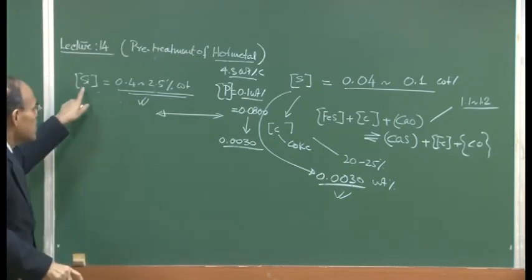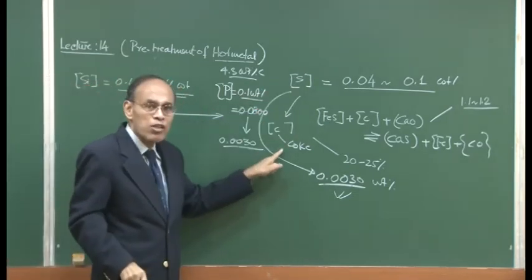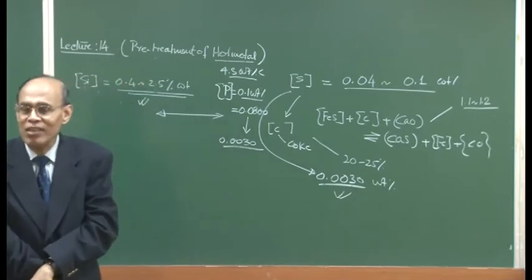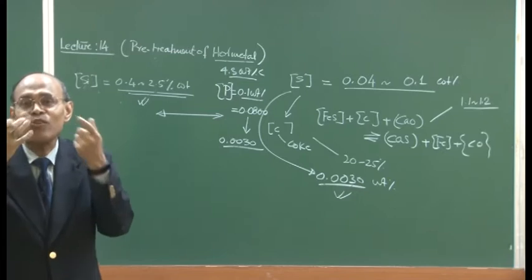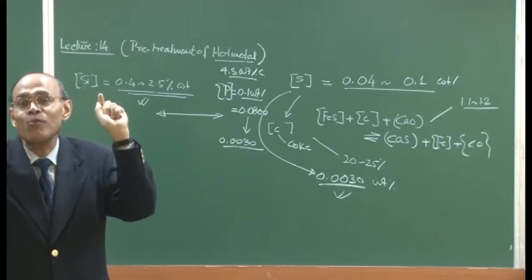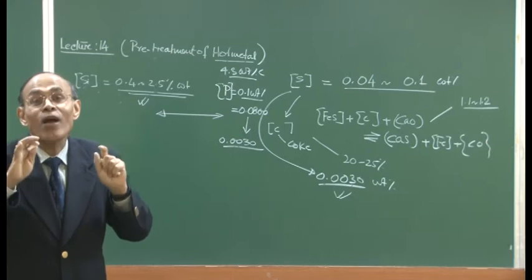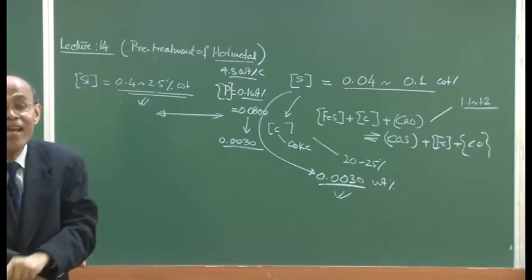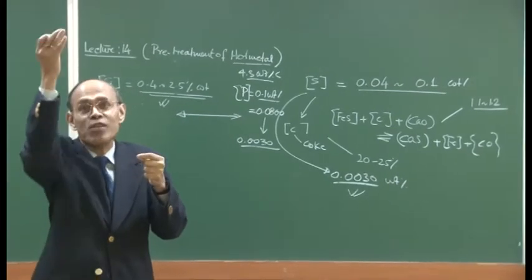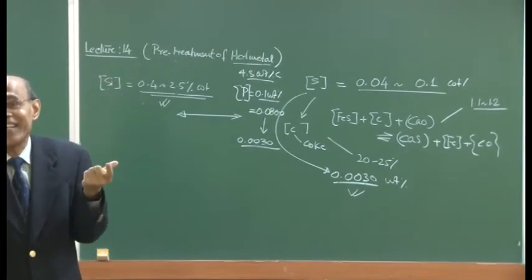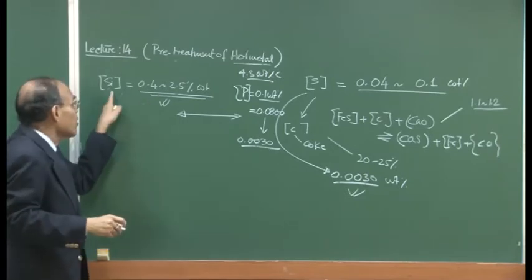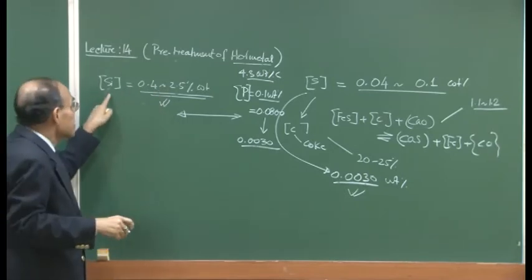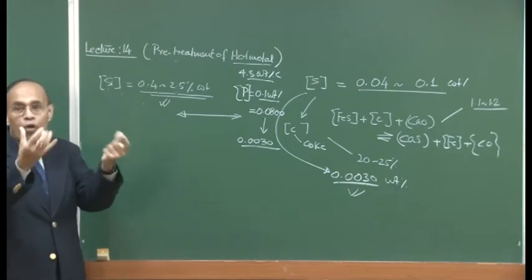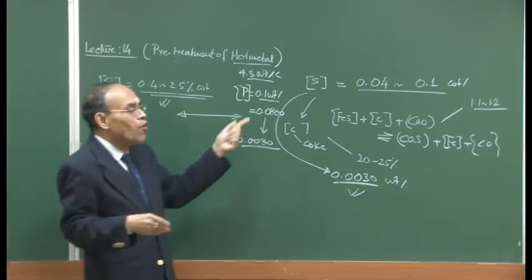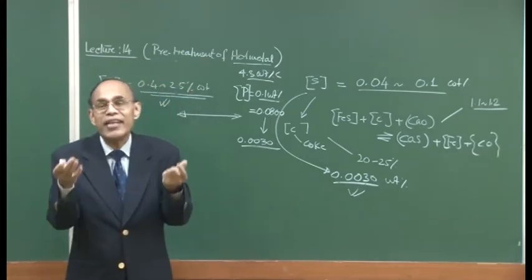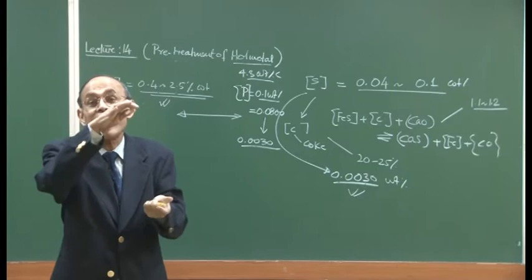If you can control silicon, sulfur and phosphorus through pretreatment, then it turns out that there is no silicon to be removed in steel making, no sulfur to be removed, no phosphorus to be removed. In that case, you have to just eliminate carbon. Okay? And the carbon oxidizes and leaves as carbon monoxide, so you do not generate any slag. Oxidation of silicon will generate silica, and as a result you will have to add flux to form calcium silicate, that is the slag phase. Similarly, if you want to eliminate phosphorus, phosphorus will be tied up as calcium phosphate, so you have to add calcium oxide, so slag is going to be generated.